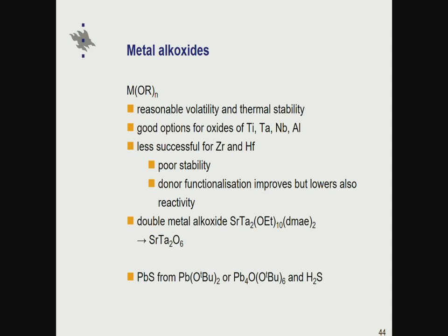Okay, after the metal halides, I guess the next group of precursors quite extensively studied in ALD were metal alkoxides. Ulla was talking about alcohol molecules producing these alucones and related materials. In this case, these are monoalcohols, and they are now rather good volatile compounds. Quite limited choice of metals, however, but especially for titanium, tantalum, niobium, these have been perhaps even dominating precursor types in ALD in general. Aluminum alkoxides are pretty good as well, but there is TMA, so there is not so much interest to have alkoxides for that reason.